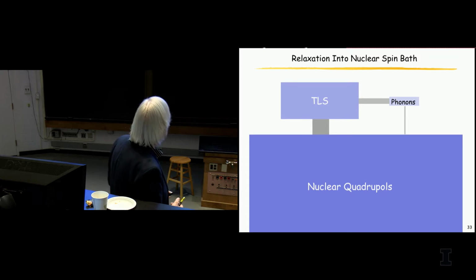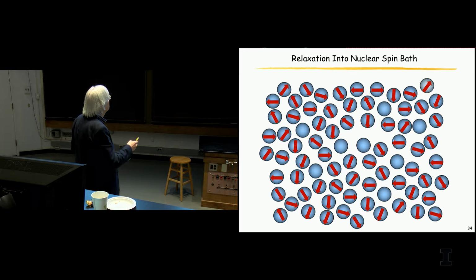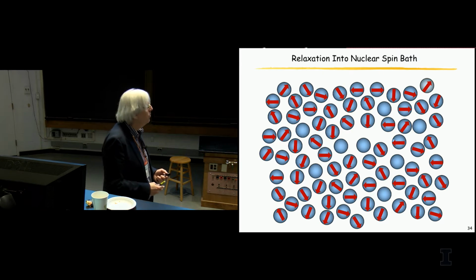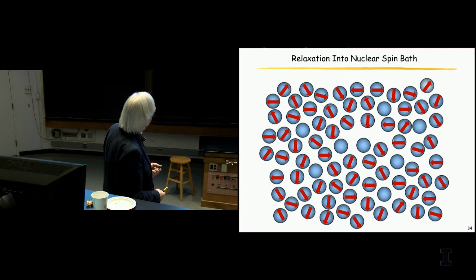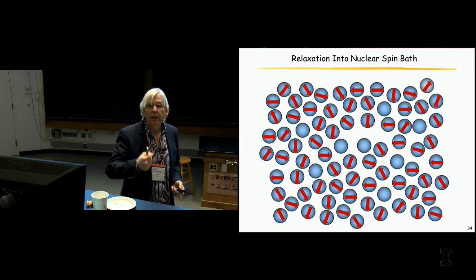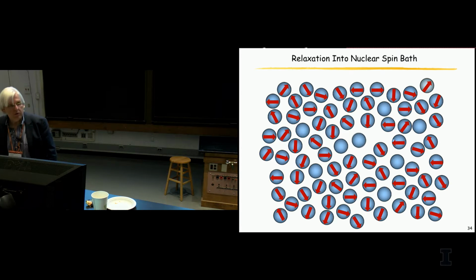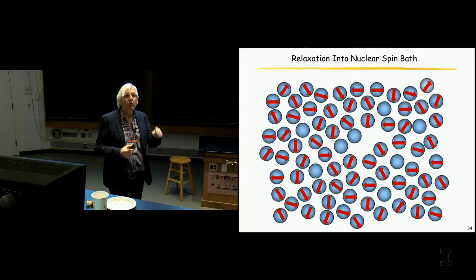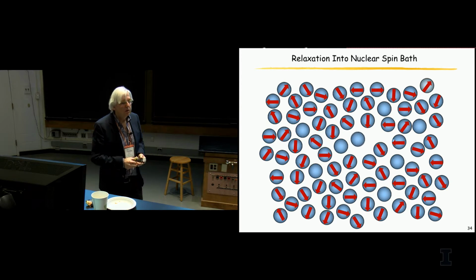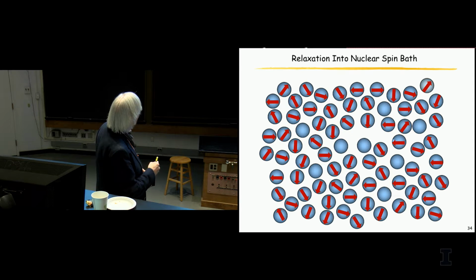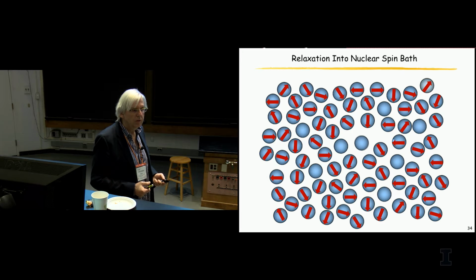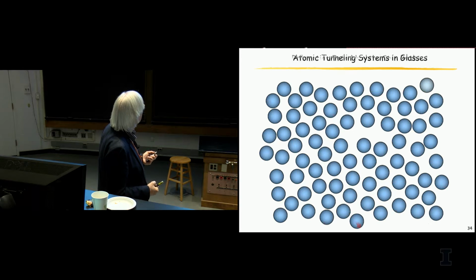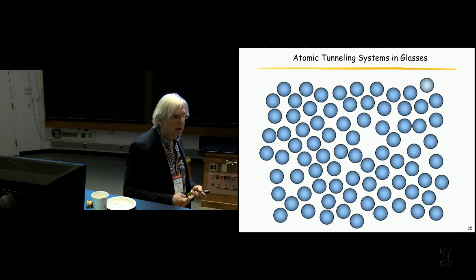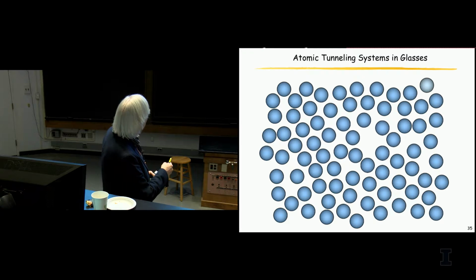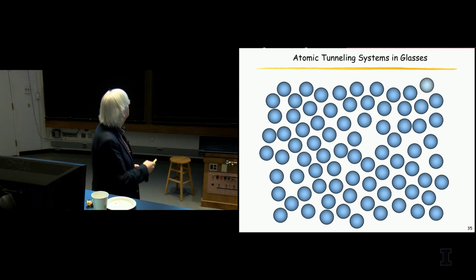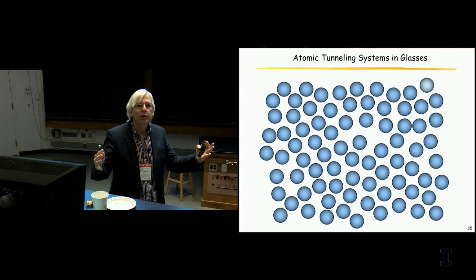How does this happen? The idea behind that is the following. I have our atom, which is tunneling, surrounded by a lot of systems which have spins. So when it tunnels, it has a huge deformation potential, so an elastic dipole or quadrupole, which is of the order of 1 eV, which is 10,000 Kelvin. So if you have 10,000 Kelvin acting here, all those surrounding atoms wouldn't stay in place. You perturb them. And I would rather look at such a picture now. So if a tunneling system, it's not clear what you call the tunneling system here, but if you remain to say this atom here is the tunneling system, then the matrix around it moves a lot.